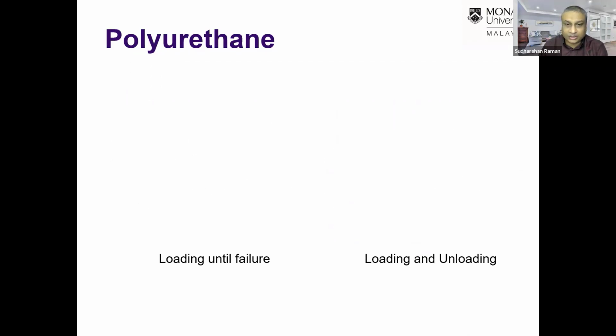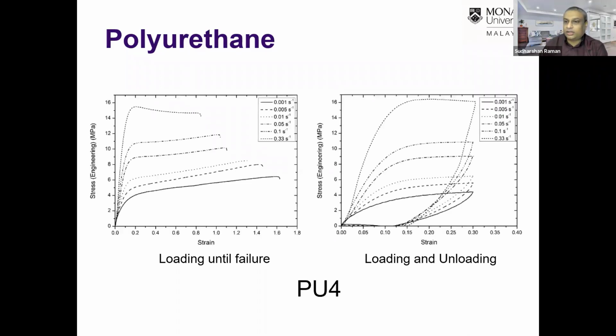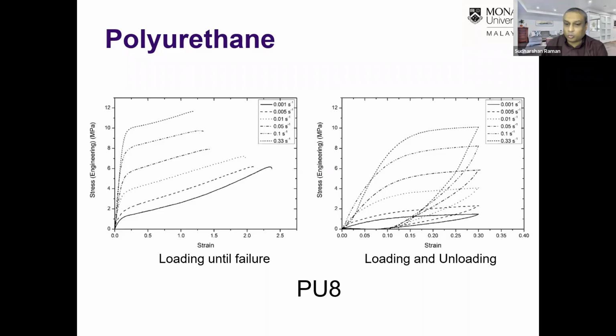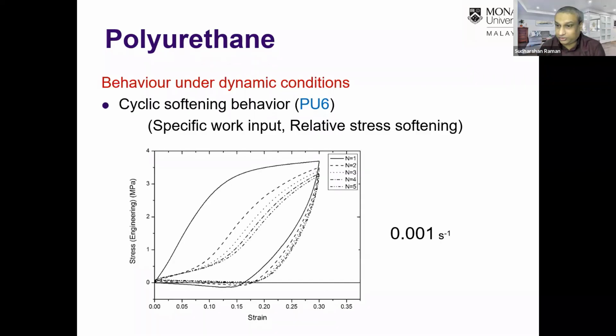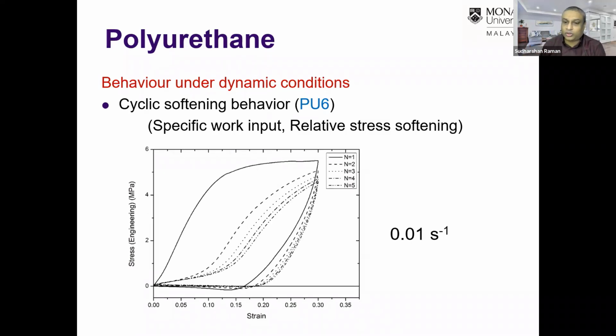Okay, we tested, as I mentioned, these 4 different polyurethanes, and we shortlisted 1 to undergo further testing, which is PU6 with 6% plasticizer, under dynamic condition, where we tested the cyclic softening behavior at different strain rates of 0.001, 0.01, and 0.1. Okay, to look at the cyclic softening behavior of the material. So in the next stage, subsequently, we only use PU6 in all our experimental work.